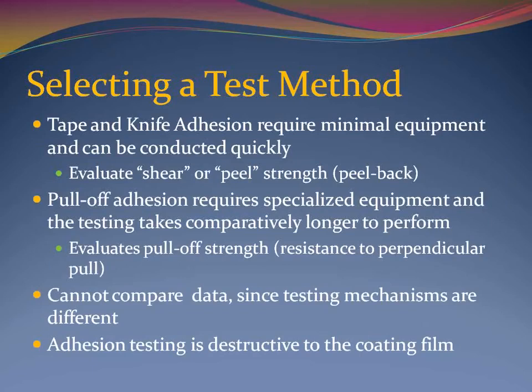Generally, the tape and knife methods are considered field test methods since they do not require any special equipment and can be conducted rather quickly. Tensile or pull-off adhesion requires instrumentation and takes comparatively longer to perform. However, the instruments used to test pull-off adhesion strength of coatings are portable, and testing can and is routinely performed in the field. The tape and knife adhesion tests are used to evaluate the shear or peel strength of a coating, while the pull-off test is used to evaluate a coating's tensile strength or its resistance to a perpendicular pull. Since the testing mechanisms are different, the results obtained from each test should not be compared. Also, any type of adhesion test is destructive — the coating in the area where you perform the test will be damaged and oftentimes must be repaired.